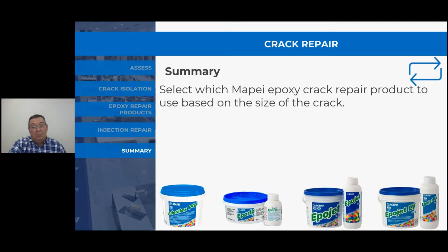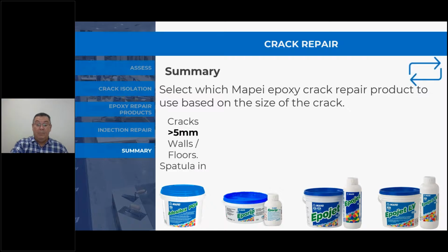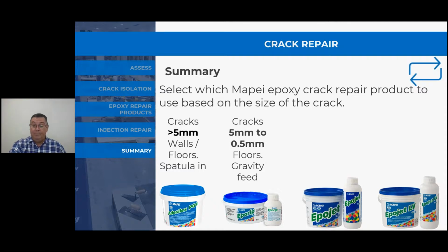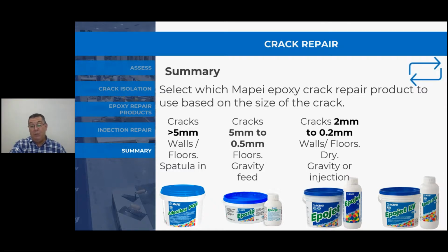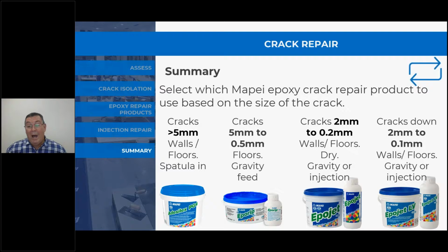Always select which Mapei epoxy crack repair product to use based on the size of the crack, and they can be used in combination. It's not uncommon to use a low viscosity crack repair and then seal the surface with a paste like Adesilex PG4. So for cracks greater than 5 millimeters, or for sealing the surface, Adesilex PG4. From 5 down to 0.5, EpoRip. From 2 millimeters down to 0.2, we would use the EpoJet. And from 2 millimeters down to 0.1, we would use the EpoJet LV.